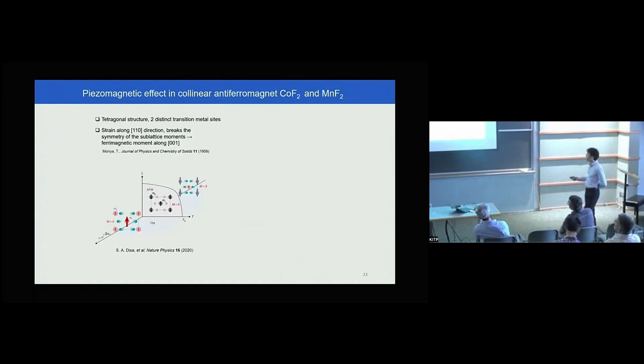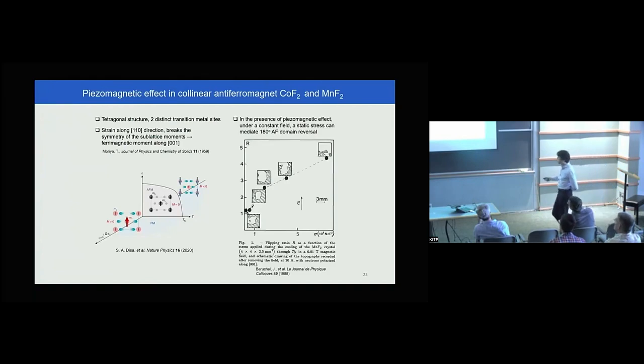Moriya and Borovik-Romanov pointed out that this is a tetragonal structure, and actually strain along the 110 direction can break the symmetry of the sublattice moments and induce a ferrimagnetic state. So the magnetization can point either up or down depending on the sign of the strain. So whether tensile or compressive, you can change the magnetization direction. Under a magnetic field, of course, you can stabilize one of those magnetic states, and then in the presence of the piezomagnetic effect, the static stress can mediate 180-degree antiferromagnetic domain reversal. This has already been done in the 1980s. So strain control of antiferromagnetic insulators has already been made, but there has been no such case in metallic or Weyl metallic